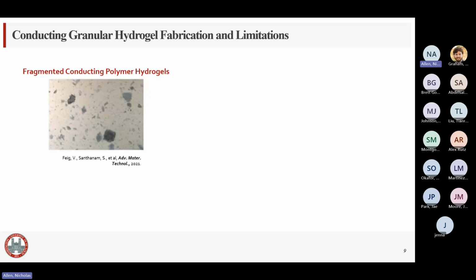They've broken them up by extruding the hydrogels through smaller and smaller nozzles, or utilizing a homogenizer, which is basically a glorified emulsion blender, to just break that hydrogel up over and over again until they get micron scale hydrogel particles. And the granular hydrogels formed through this fabrication method have great bioelectronic functionality. So when we're looking at conducting polymer hydrogels, we use a term called conductivity to evaluate how well the material will act at bioelectronic interfaces. And essentially, conductivity measures how well the material transduces electrons throughout the bulk of the material. So the higher the conductivity, the better it is likely to work at transducing signals back and forth. And this material, because they fabricated it from a pure conducting polymer hydrogel, has conductivity comparable to hydrogels already successfully used at bioelectronic interfaces. The ability to act in that manner is fantastic.